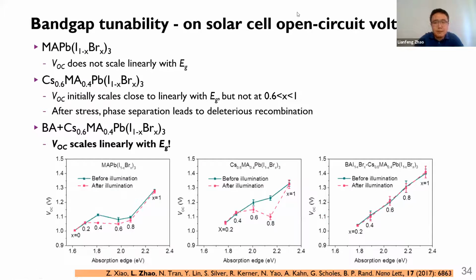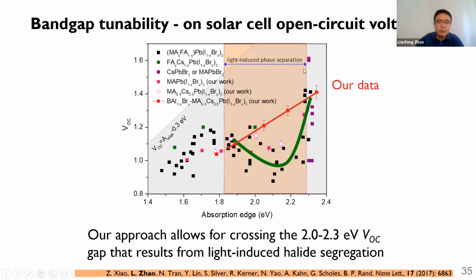This strategy can also be used for perovskite solar cells. As you can see, the open circuit voltage for the control samples cannot be tuned correspondingly with the absorption edge. But using our method, the open circuit voltage can be linearly tuned with the band gap. This can really get the benefit of the high open circuit voltage from using a wide band gap semiconductor. And here we compared our data with reported results, and we filled the voltage gap for the mixed halide wide band gap semiconductors.